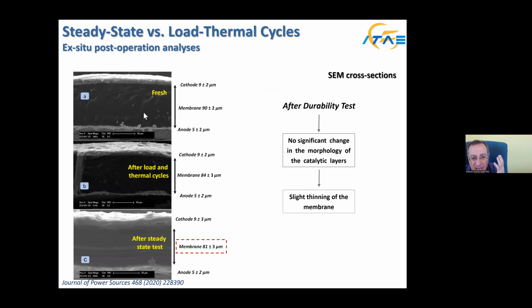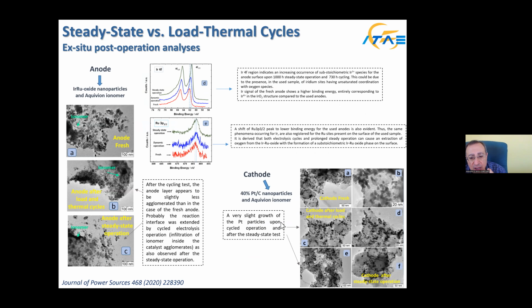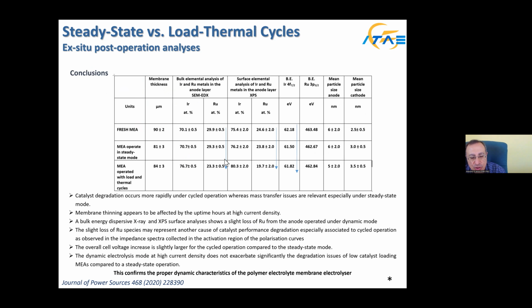These are, as an example, MEAs dismantled after a prolonged durability test, showing very little membrane thinning. Also, the catalyst morphology is not changing much. What is really changing is the electronic properties, the oxidation state of the anode catalyst, and some ruthenium dissolution.